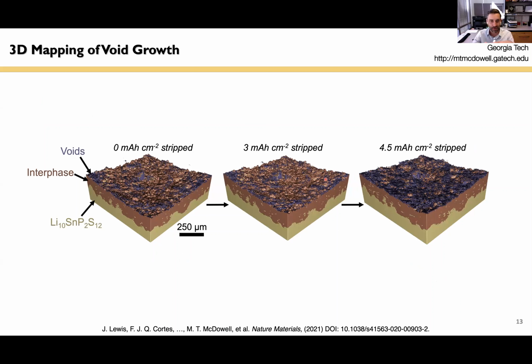So this is an illustration of a three-dimensional section of the interface, where we're looking at an angle down through the lithium metal. So there's lithium metal on top of this, but we're not visualizing it in this visualization. The solid electrolyte is below, and there's interphase that's also grown below, which we segment out. But what we are showing on top of the solid electrolyte are these purple spots, actually purple voxels. And these purple voxels are the voids.